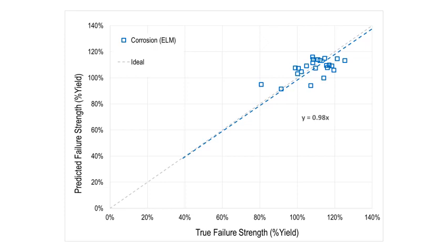I think you'll find that agreement is quite a bit better than any of the B31G models, including RSTRENG, and actually including the more recently developed P-squared model. Now, like I said, I've got a spare secant term that I'm not sure quite how it all fits in. I still have to resolve that, but what I can see so far is that the square root relationship seems to be very effective, because that square root relationship is built into this ELM model, the GEM's ELM model. So things seem to be pointing in the right direction.